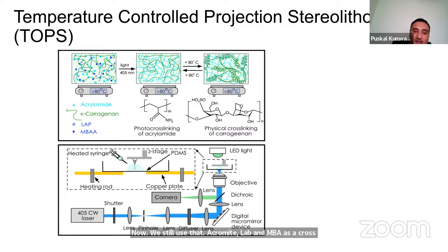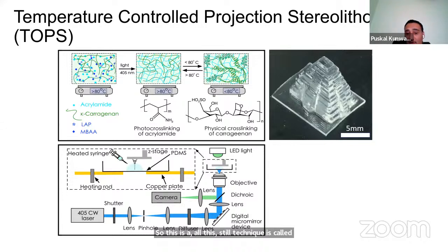Now to make this whole photoresin into solution, it has to be heated to 80 degrees Celsius. So we made a sample holder using a heat plate and copper, which maintains the holder at 80 degrees Celsius. While printing, it remains a solution so that we can print the structure. This technique is called temperature-controlled projection stereolithography. Based on that, we printed